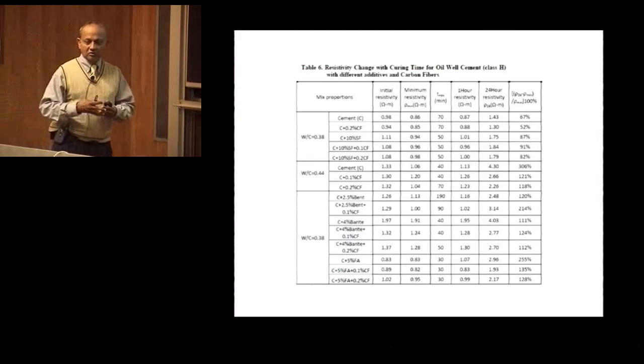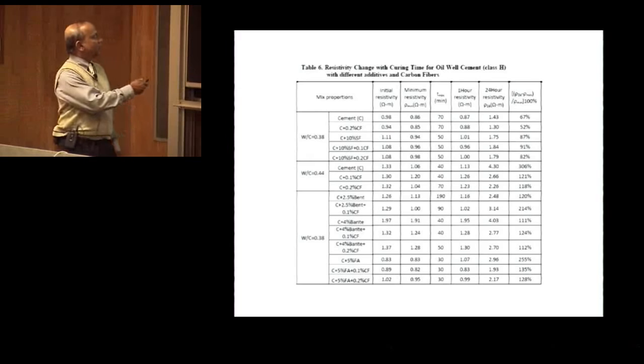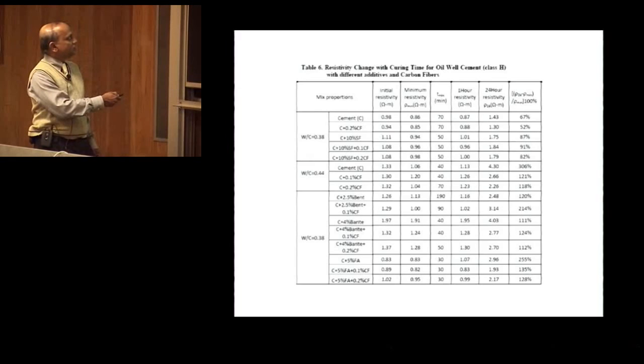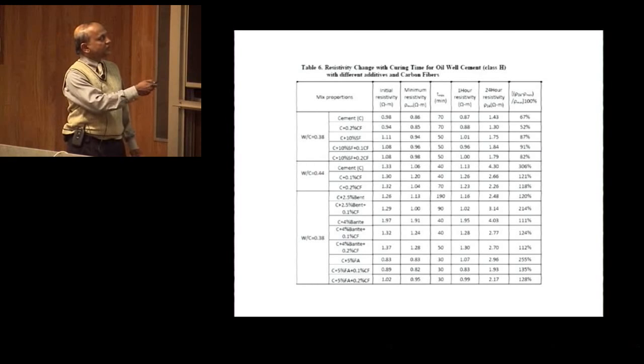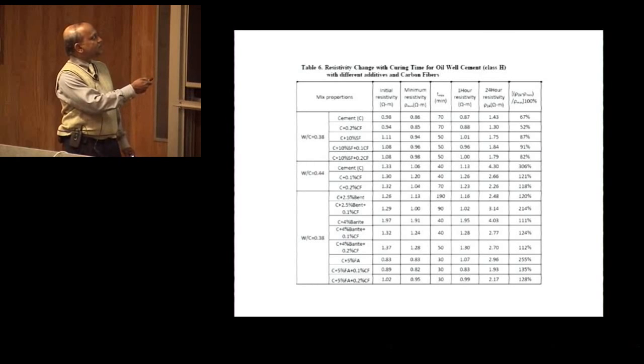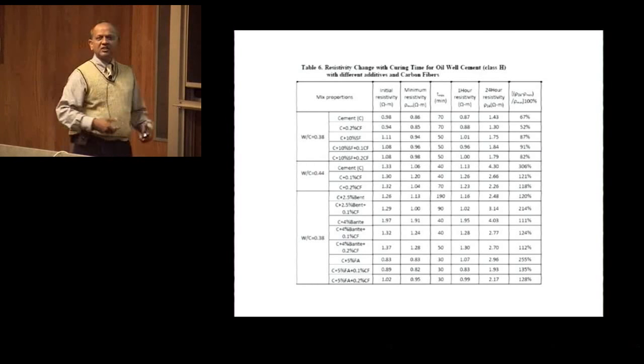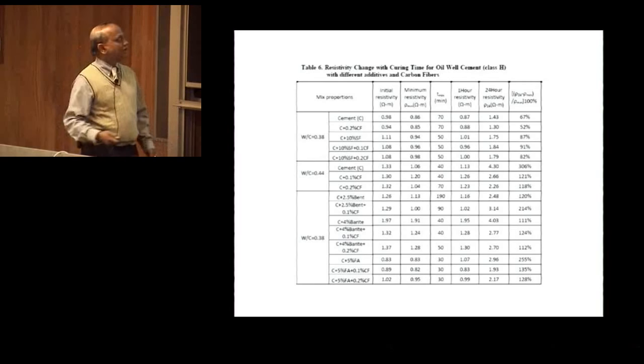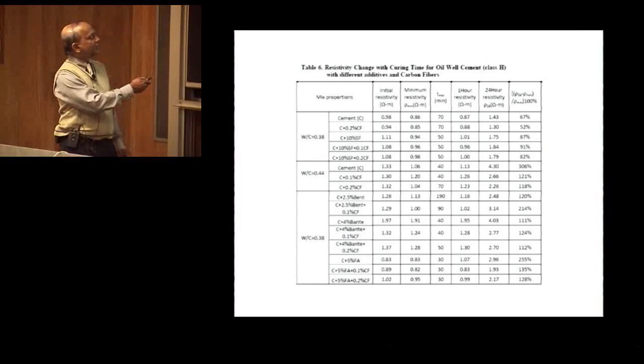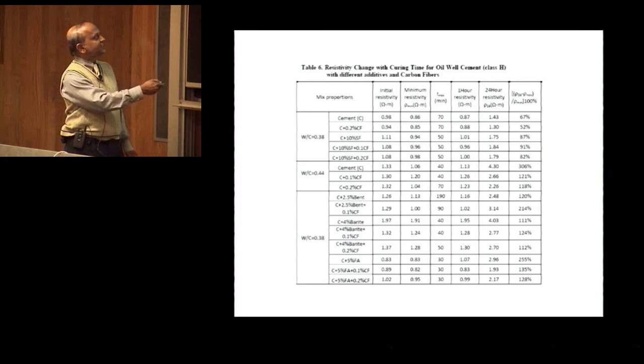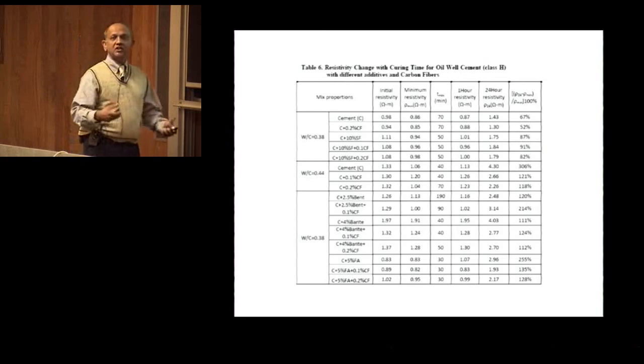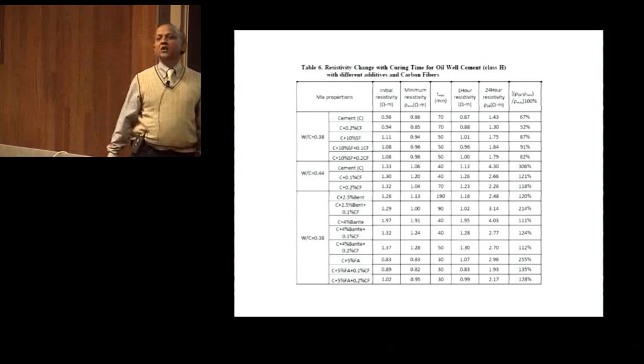Actually, this will also be on display. So you can see how, when the water to cement ratio is changing, the resistivity changes. Let's look at this one. The resistivity at a water to cement ratio of 0.38, which is a typical mix that they use in the field, is about 1. And then it goes to about 0.86. And then in 70 minutes, the minimum resistivity, and it changes, and we see a 67% or more change in the resistivity within 24 hours.